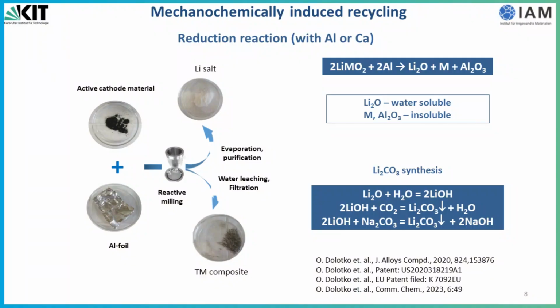If to explain briefly our method, it can be shown like that. So, as active cathode materials with a general formula of lithium metal oxide, when it's ball milled with a reducing agent like aluminium or calcium, during the ball milling a reduction reaction occurs, where lithium metal oxide is reduced to lithium oxide, aluminum oxide, and with formation of a metallic composite.